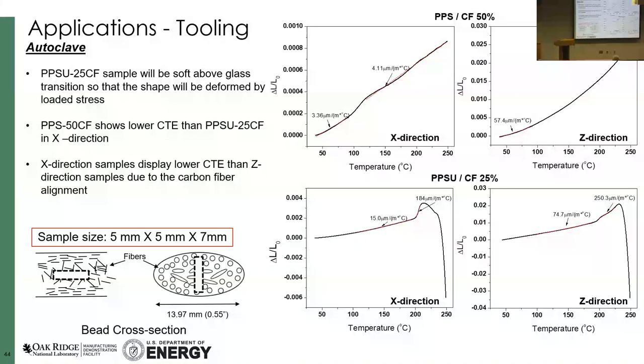So to be able to do a TMA, your sample is this big, right? 5 by 5 by 7. Guess what? Your bead is about half an inch. And you have a distribution of fibers on there. Highly aligned, random, highly aligned again. So it depends on where you get your samples from. So the reason that I'm saying that scalability right now didn't only affect the manufacturing method, it affected the characterization method as well. The current standard characterization method is not valid currently because where should I take my samples? I have very heterogeneous material and CTE is an intrinsic value of a material. I can get some values and average, but would this mean anything to the modeler of the tool?